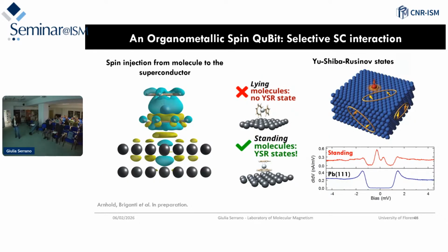The nice part of that is that we understood that the lying molecules were not producing any Shiba state in the superconductor, within the band gap of the superconductor, but the only molecules that were producing Shiba states were the standing ones, and we could also control the extent of coupling. This is because the standing molecules have the dz² orbital, the magnetic orbital, directed perpendicularly to the surface, so it has a higher energy match with the surface.